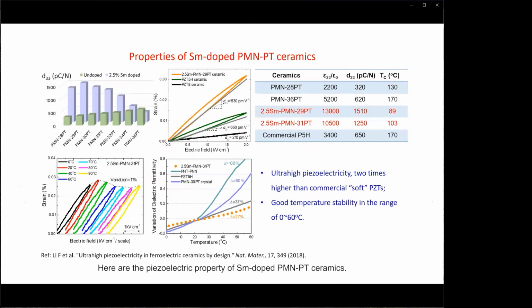Here are the piezoelectric properties of samarium doped PMN-PT ceramics. The highest piezoelectric coefficient d33 is around 1500, which is about 2 times higher than that of commercial soft PZT ceramics. Compared to P5H ceramics and PMN-PT crystals, samarium doped PMN-PT also has an improved temperature stability, as shown here. Thus, we think that samarium doped PMN-PT ceramics is a very good choice for applications around room temperature.